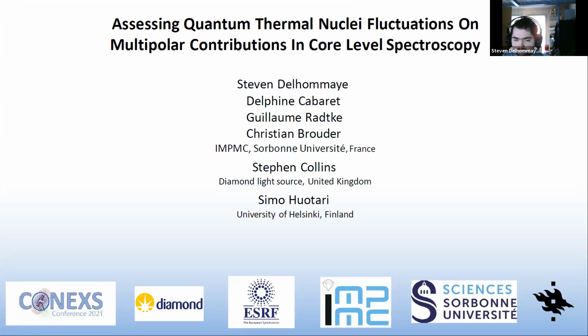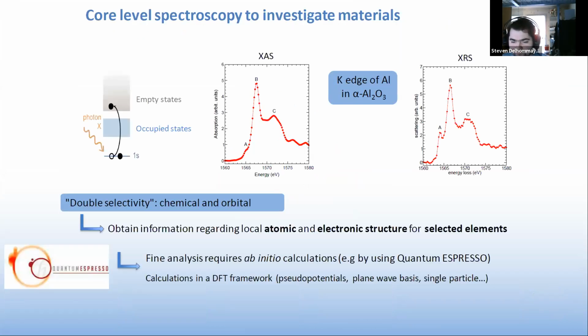in this work. So as many of you, I studied the use of core level spectroscopy techniques to investigate materials. They're called that way, of course, because they involve the excitation of a core level electron towards empty states. So here, using X-rays. And this technique, as I think it was Amélie told us yesterday, they are very interesting because they present a double selectivity, both chemical and orbital. And that means that because each element has its unique core level energies, we can obtain, using these techniques, precise information regarding local structure or electronic properties for specific elements that we choose in the materials.